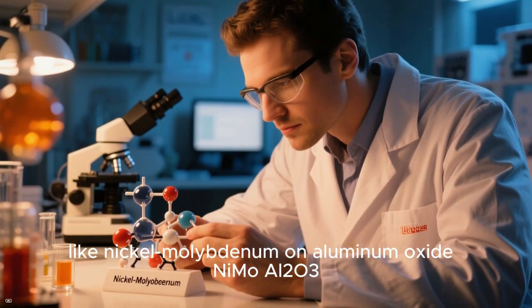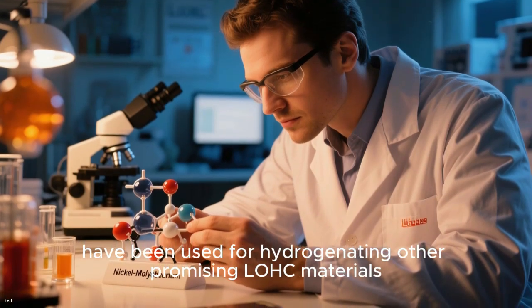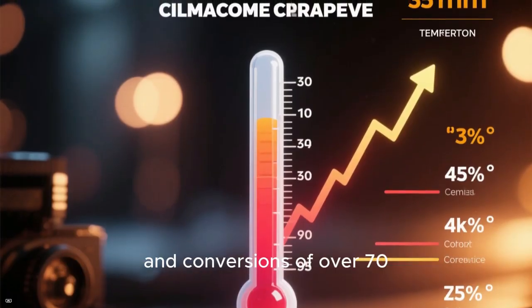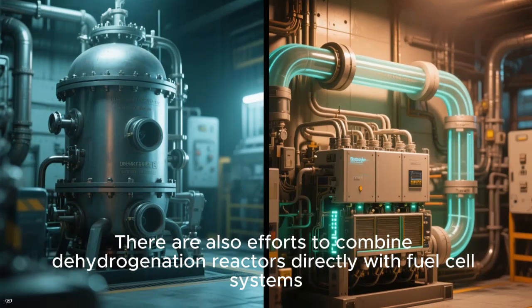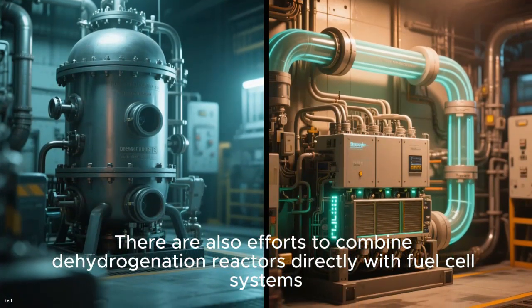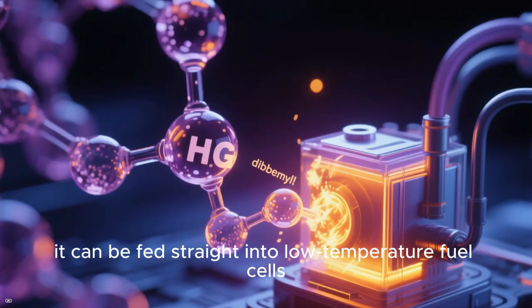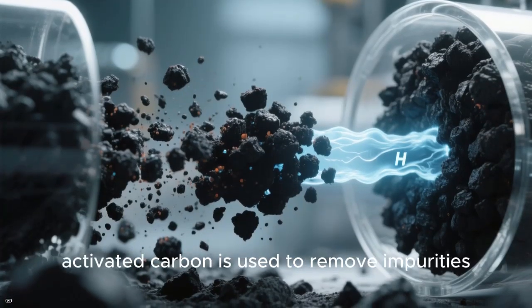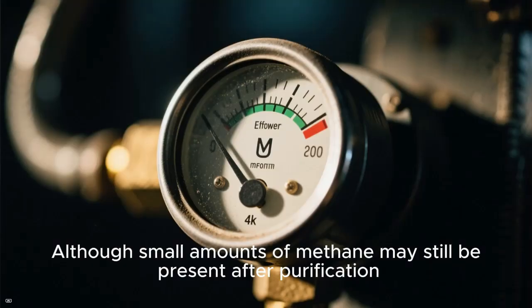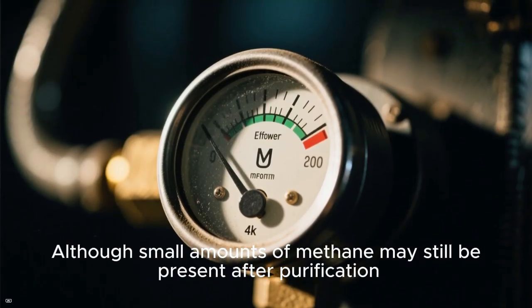In other studies, different catalysts like nickel molybdenum on aluminum oxide (NiMo/Al2O3) have been used for hydrogenating other promising LOHC materials, such as phenanthrene. These reactions happen at higher temperatures, and conversions of over 70% have been achieved, showing strong potential for these catalysts in hydrogen storage applications. There are also efforts to combine dehydrogenation reactors directly with fuel cell systems. For instance, when hydrogen is released from dibenzyl toluene, it can be fed straight into low-temperature fuel cells. To ensure the hydrogen is clean, activated carbon is used to remove impurities. Although small amounts of methane may still be present after purification, the fuel cells continue to work efficiently without losing power.